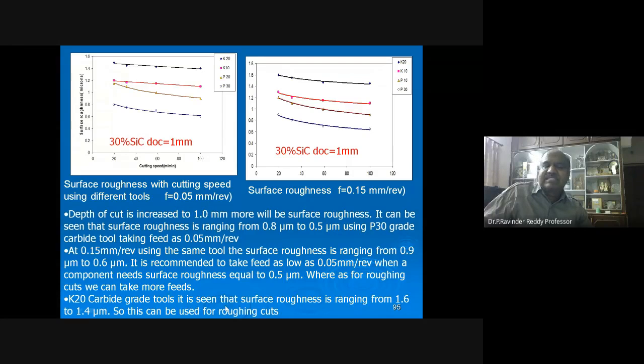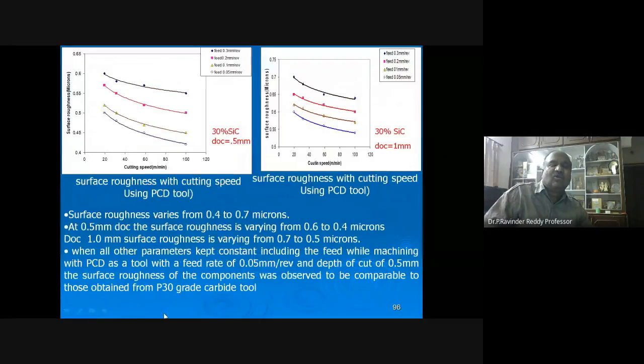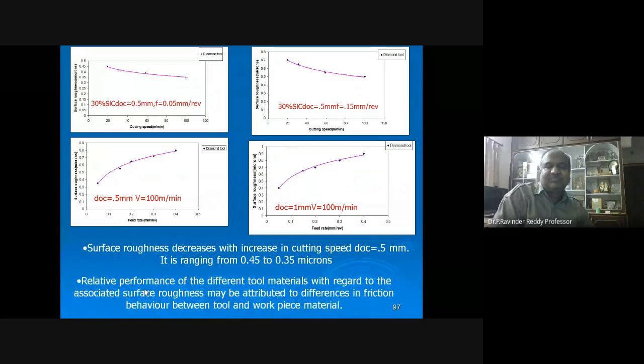With K20 carbide grade tools, the surface roughness is seen to range between 1.6 and 1.4 microns. So each tool we have conducted, even PCD, with all the other parameters kept constant, including the feed. While machining with PCD as a tool with a feed rate of 0.05 mm per revolution and depth of cut 0.5 mm, the surface roughness of the components was observed to be comparable to those obtained from the P30 grade carbide tool. The relative performance of the different tool materials with regard to the associated surface roughness may be attributed to differences in friction behavior between the tool and the workpiece materials.